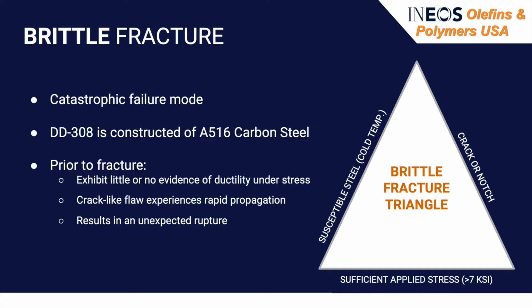Brittle fracture is considered a catastrophic failure mode as it occurs rapidly without warning. The diagram on the right indicates the three required conditions for brittle fracture: crack or notch present, sufficient applied stress, and susceptible steel as a result of cold temperatures. In order for the team's solution to be effective, it needed to ensure that one of these conditions was not met.